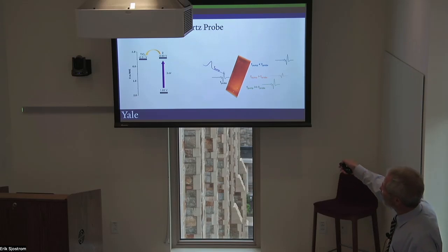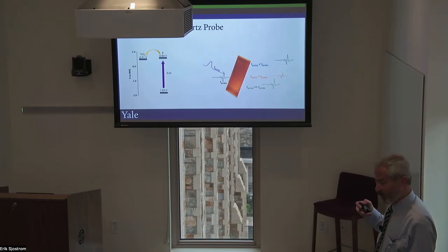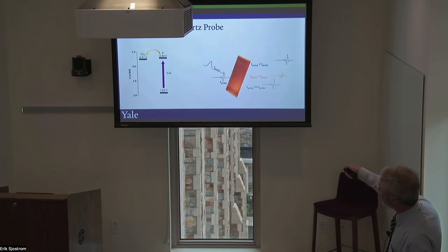So just to give you a little bit of an introduction, terahertz spectroscopy is a probe of electrons in the conduction band. The technique we do is we excite, and electrons are injected into the conduction band with a visible photon. They'll be now mobile and they absorb terahertz radiation, which is a very low energy frequency that is absorbed strongly by conduction band electrons. And so we do a pump-probe experiment. We have a visible pump which excites this transition. Typically we use around 400 nanometer, about a 10 femtosecond pump pulse. And we follow it with a terahertz probe pulse with a variable time delay.